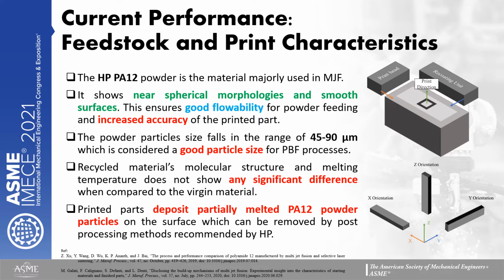In the section of current performance, first I'm going to discuss the feedstock and the print characteristics. The HP PA12 powder is the material majorly used in MJF printing. It shows nearly spherical morphologies and smooth surfaces. This ensures good flowability of powder feeding and increased accuracy of the printed parts. The powder particle size falls in the range of 45 to 90 micron, which is considered a good particle size for powder bed fusion processes.